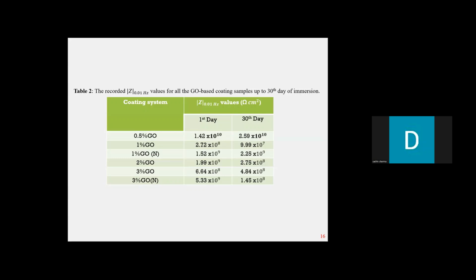So table 2 illustrates all the Z impedance values, but it was at the same order of magnitude, 10 to the power of 10 as well. And we can look at the 3 weight percentage. The values were at 10 to the power of 8. And for the 1% GO that was fabricated without the influence of vacuum, there was a drop by an order of magnitude from 10 to the power of 8 to 10 to the power of 7.